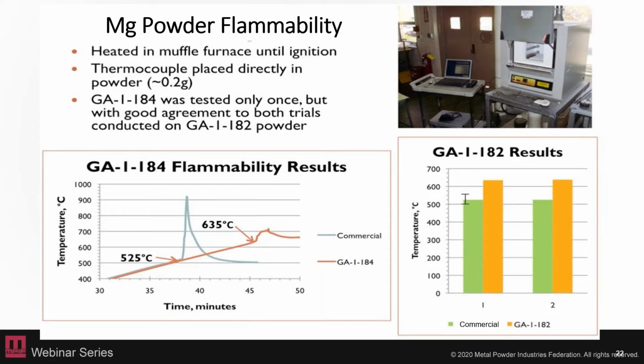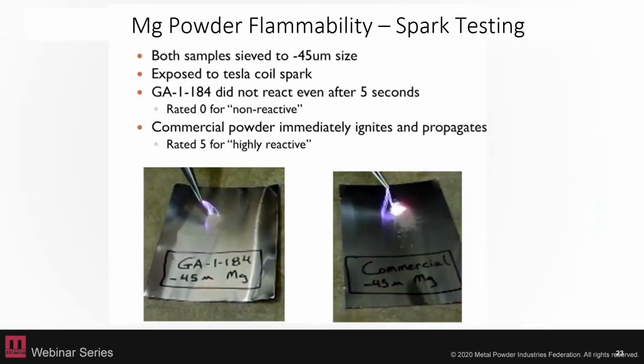And just as an example, another test we run on any of our powders coming out of the atomizer is what we call a spark test. So these are the same size powders, and then they're exposed to a Tesla coil. The powder that was created with the oxyfluoride coating did not react. And we rate that internally. We just have a comparison scale, 0 for non-reactive, and then the commercial powder immediately ignited, and that flare propagated. So that would be a 5 rating for highly reactive.